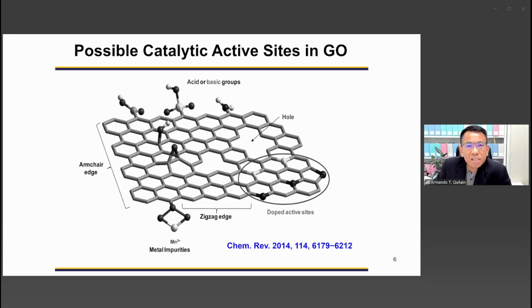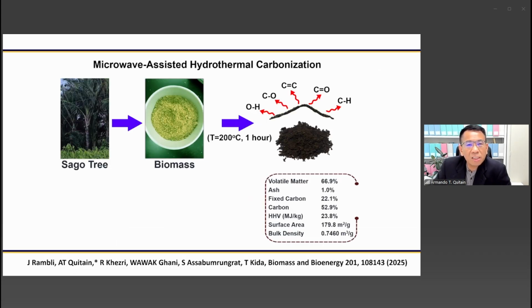So the presence of these active sites makes the graphene oxide surface highly acidic, as I have mentioned. Now, these active sites or functionalities on graphene oxide surfaces can also be found in hydrochar. We did research on the conversion of biomass into hydrochar under hydrothermal conditions. And we also found the presence of those functional groups on the surface of hydrochar obtained at around 200 degrees centigrade in 1 hour using microwave-assisted hydrothermal carbonization, like this one.